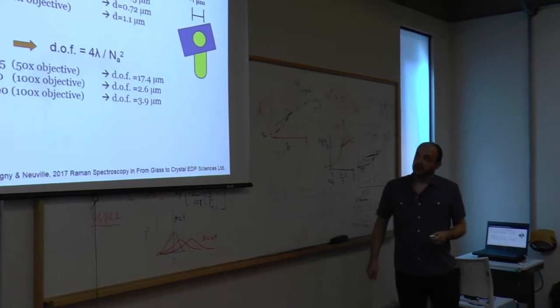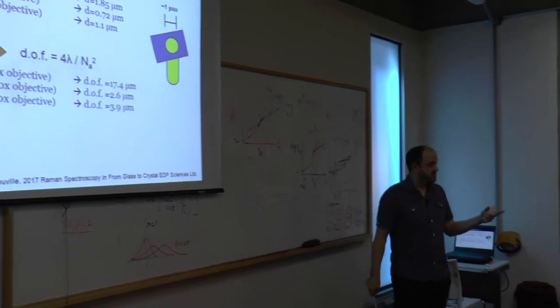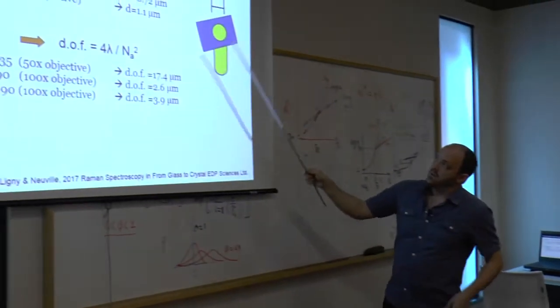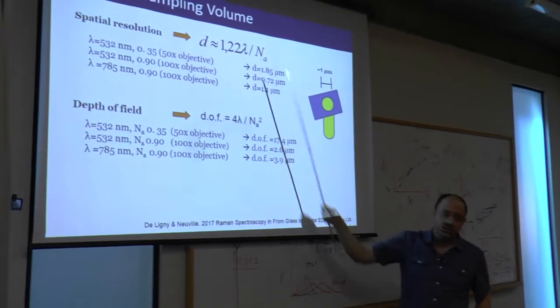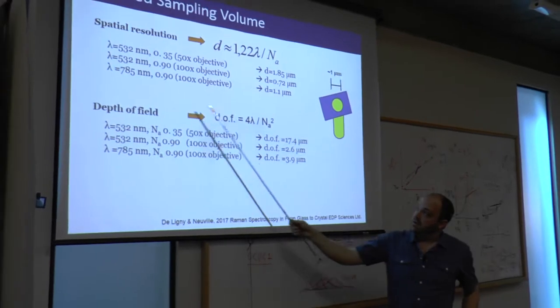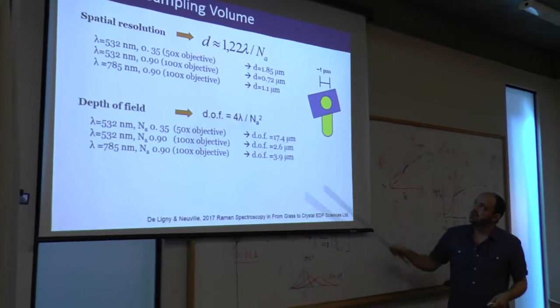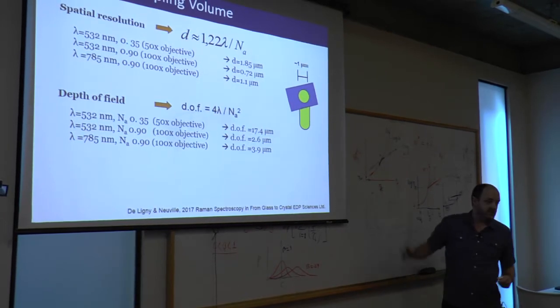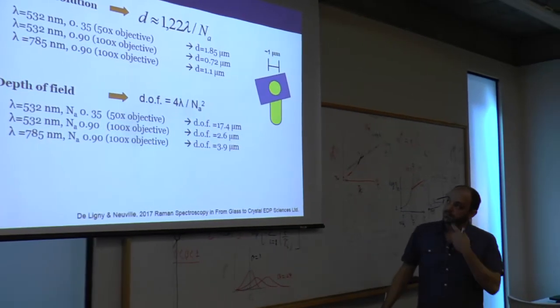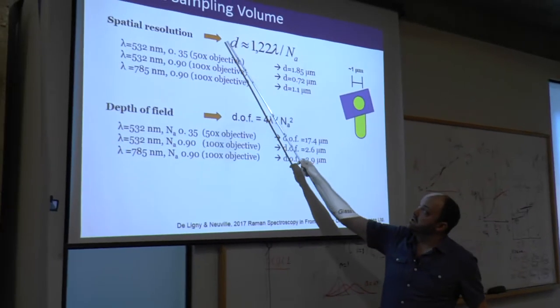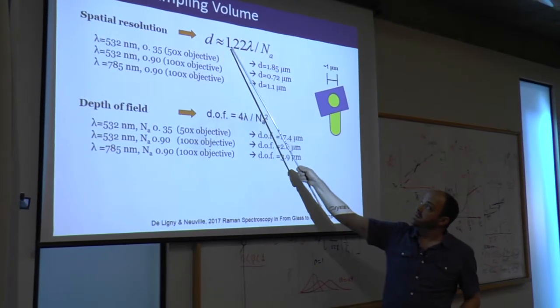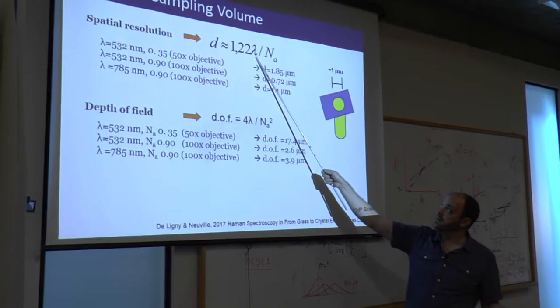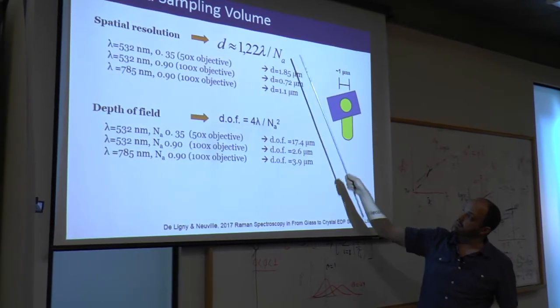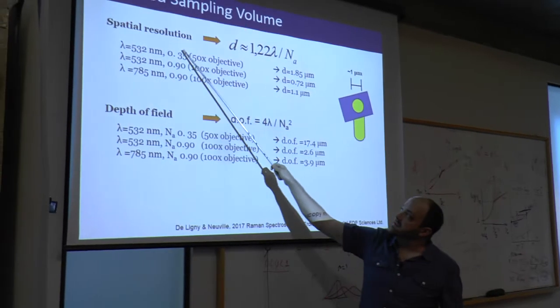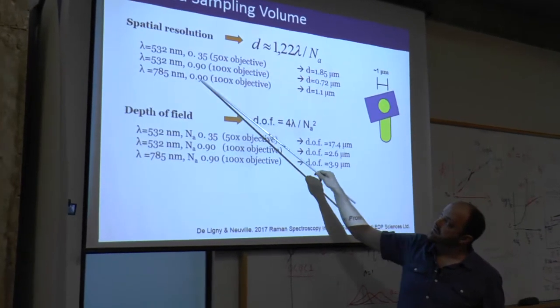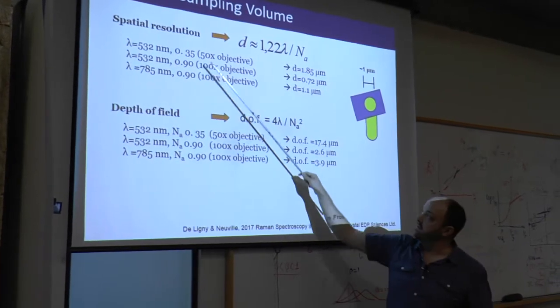In terms of the sampling volume, there was a question last class about the spatial resolution of it. There's two factors. One is the actual spatial resolution in terms of where you focus your beam, and the other is called the depth of field. And these combined give you a very crude estimate of your actual scattering volume that you're sampling. So for the spatial resolution, the width of that beam is related to 1.22 times the wavelength of excitation divided by the numerical aperture. So here are some typical wavelengths. Here are some different objectives you might be using. This is the numerical aperture that's written on the side of every objective.